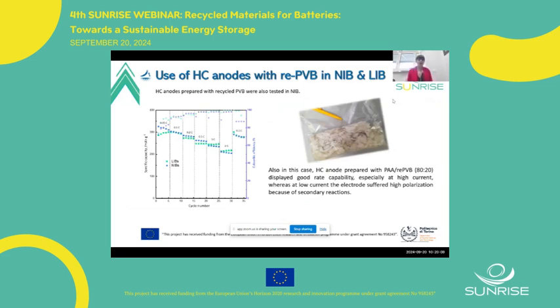Okay, then we tried the characterization with recycled PVB that we obtained from Loureiro, our partner. As we show in the picture, it is the recycled PVB with some plasticizers, and we tried to make a laminate again with 90% hard carbon, 5% conductive carbon, and 5% binder with PAA and recycled PVB 80-20%.